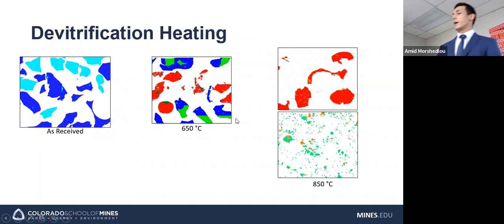So right here, I've got some SEM false color images of some of the slag as received, after heating at 650 for 2 hours and then furnace cooling, and then again at 850. We can see right here at 650, we are starting to get some devitrification, especially here and here. But this red phase right here is just a different amorphous phase, and I use that term loosely. It is distinct from the initial phases, being the copper slag and the lead slag here.